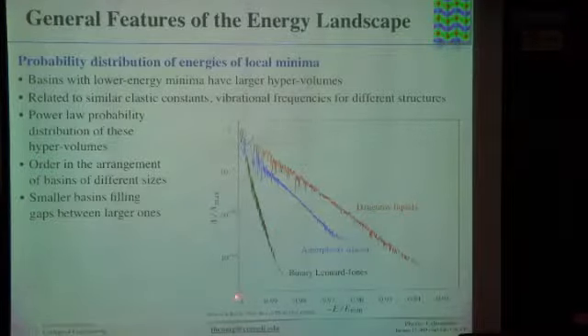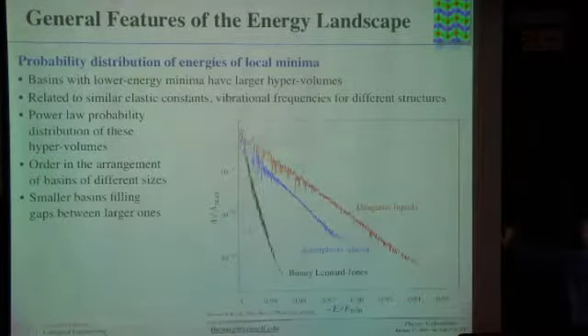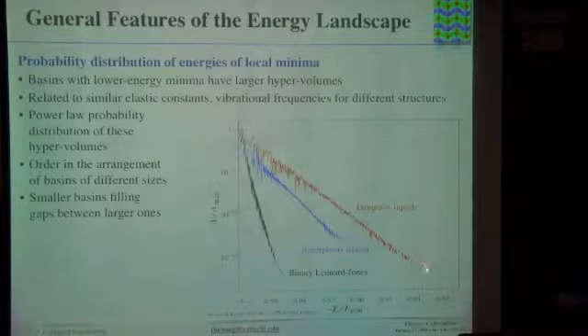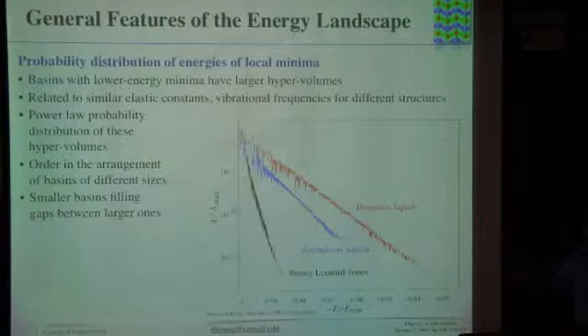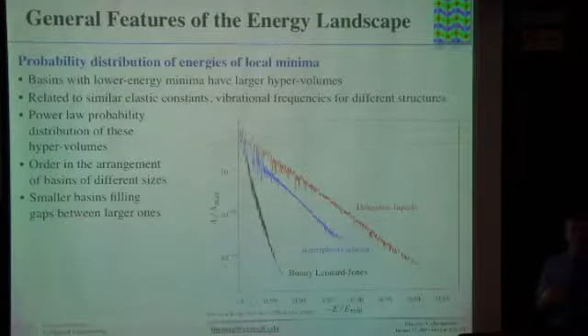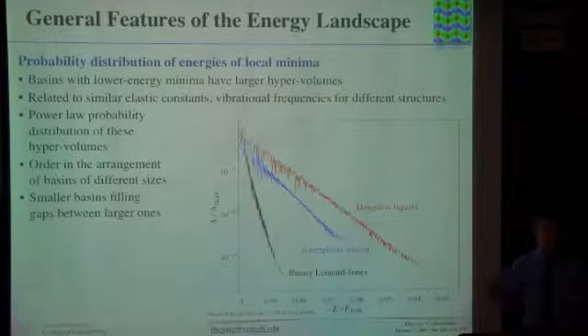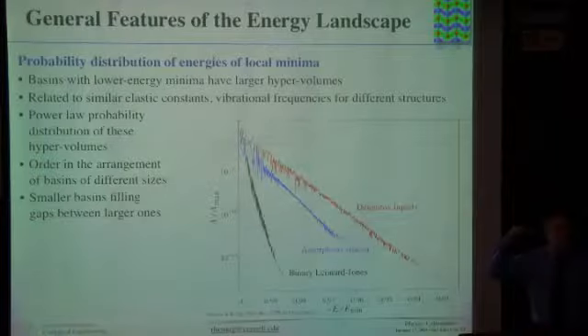They show, as a function of energy scaled to the minimum energy, so -1 is the minimum energy, that region, that volume in space, which is the basin of attraction, which you slide down into that minimum. And it follows a pretty straight line for very different kinds of models. The larger the region of attraction is, the lower the energy. That makes our job a lot easier, because what we have to find is that lowest energy structure. And we have a chance of finding it because the region I have to enter and then fall down into that minimum is actually most likely large.